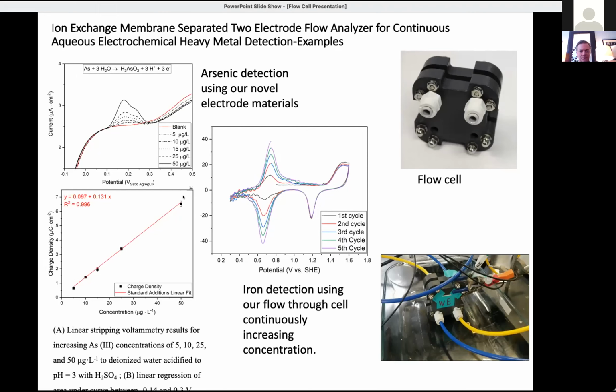We've tested our electrode materials on natural waters within the state of New Mexico with common interfering ions, ions which might be an interference, common ions in the water such as sodium, chloride, sulfate, potassium, and we still get a nice linear correlation here. Here's an example for iron, where in each one of these cycles there's successive additions of iron into the solution which is flowing through, and you see the increasing peak height indicative of the higher concentrations as it's continuously flowed through the cells.